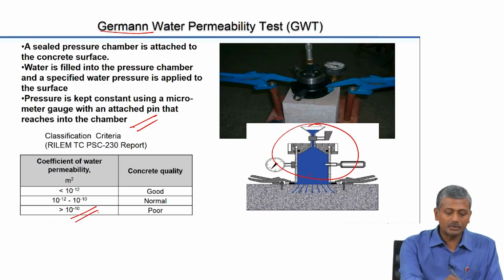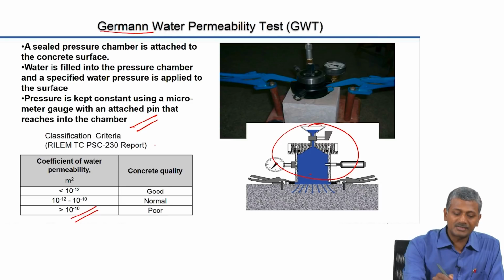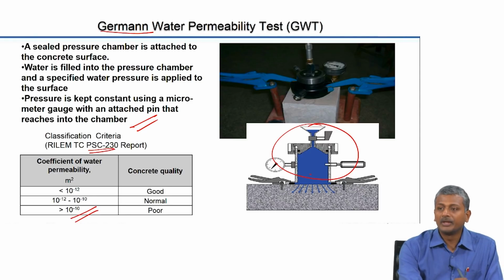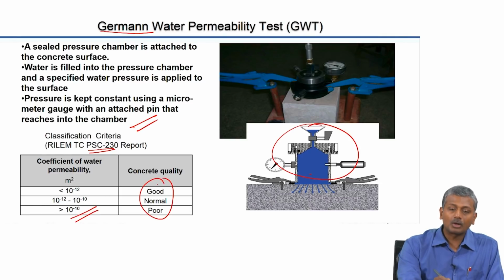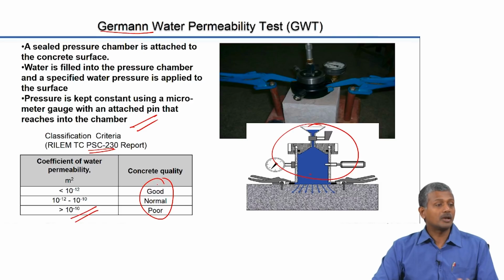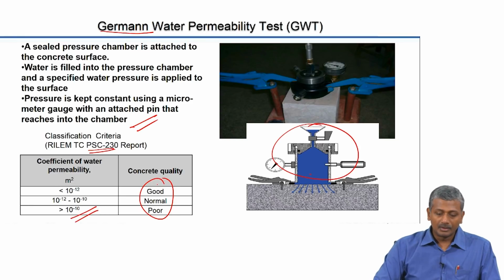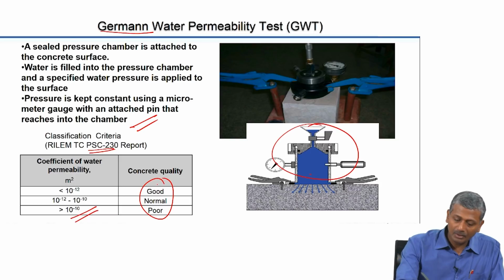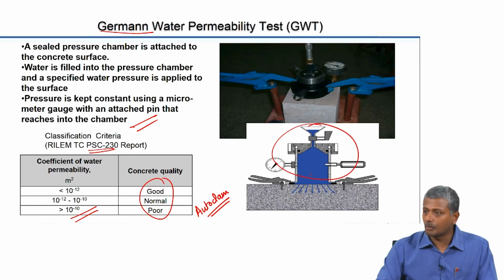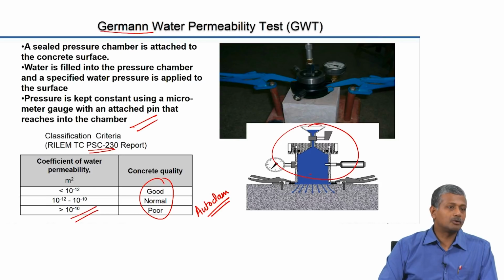Okay. And then based on the conditions that are prescribed. Of course, this is again not a standardized test. It is again covered in a report of a RILEM committee, and it tells you that for different values of permeability, the concrete quality can be assessed qualitatively. There is again no quantification here. Concrete is good, normal or poor when your permeability coefficient is so much. Okay. There are also other devices available like this. There is another device called Autoclam, which is also available in the market, which can be used to directly fix on top of your concrete structure and determine the permeability coefficient.